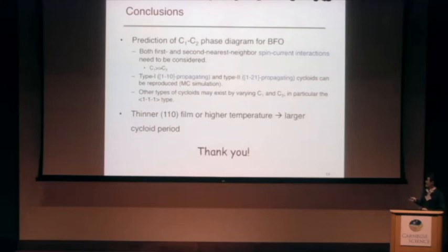And we have reproduced the type 1, type 2 cycloids. And we also predict the new cycloids, in particular the 1, -1, -1, which may actually exist. Also, the period of the cycloid in 110 film becomes longer with thinner thickness or higher temperature. Thank you for your attention.